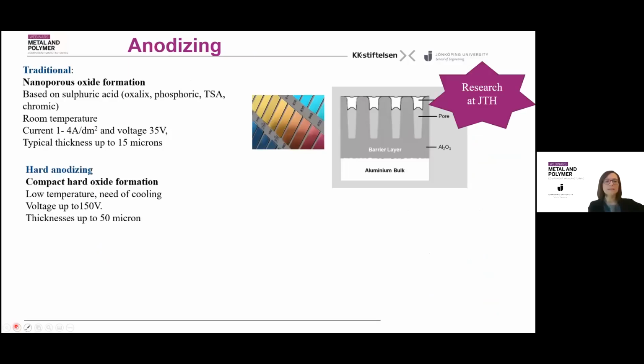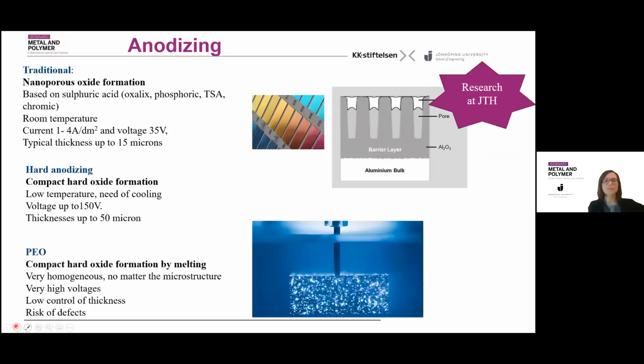There are several types of anodizing, based on different process parameters. The most common is the traditional one, where you form an oxide layer that has a very special structure, nanoporous, forming nanotubes on the surface. At the bottom, you have a barrier layer that gives protection, and then you have these nano containers that can fill up with pigments, creating beautiful final aspects.